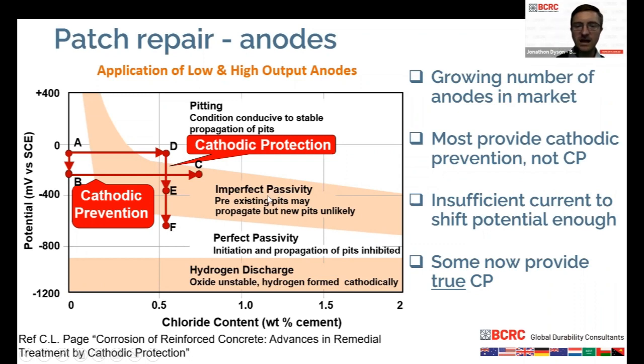Now, that zone of imperfect passivity is okay if you don't have corrosion already happening. So in scenario B, if you installed those lower powered anodes up front, or, for example, in a patch repair to protect the surrounding concrete where corrosion hasn't yet started to occur, then you've got scenario B. And what that means is you've shifted the potential of the steel reinforcement enough such that you won't get new pits occurring, which means that you can have a higher level of chloride ingress before corrosion will start to occur. So just a little bit of a shift means that you can go from, say, 0.4% weight of cement for reinforcement initiation all the way up to around about 1% before reinforcement might initiate. So that's where they can be useful, those cathodic prevention anodes. And there are also some patch repair anodes these days that are actually powerful enough to provide proper cathodic protection and achieve that higher level of potential shift in the steel.